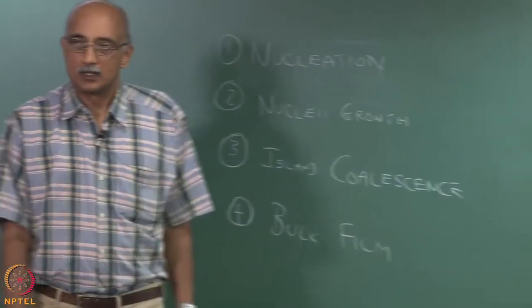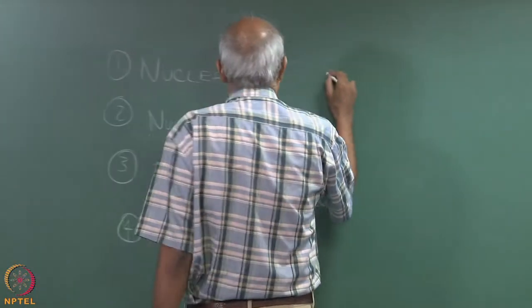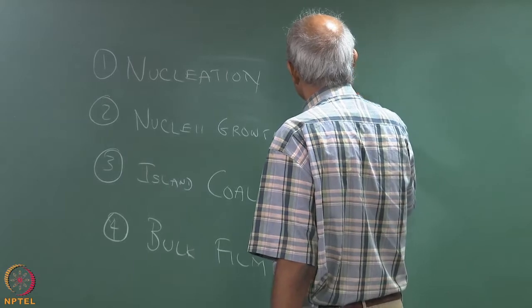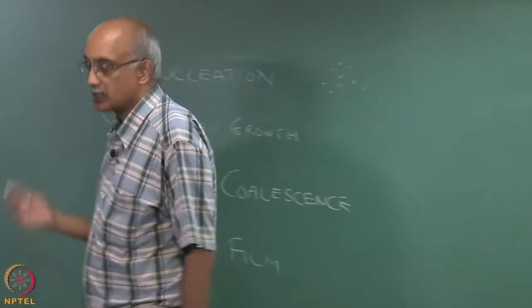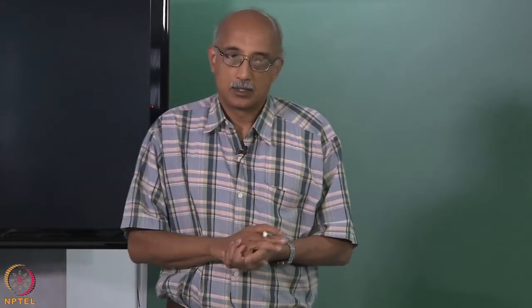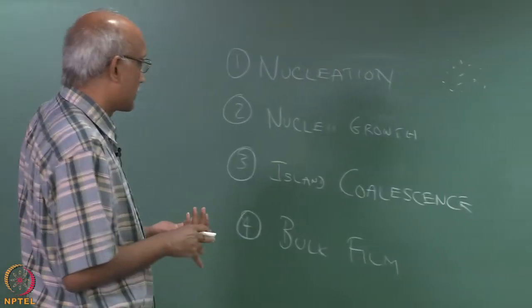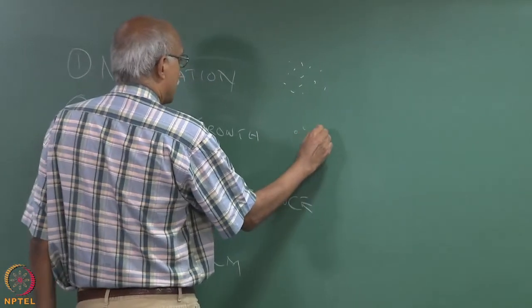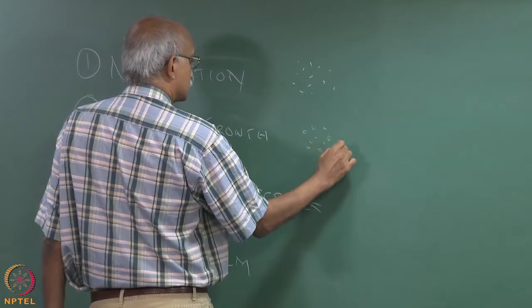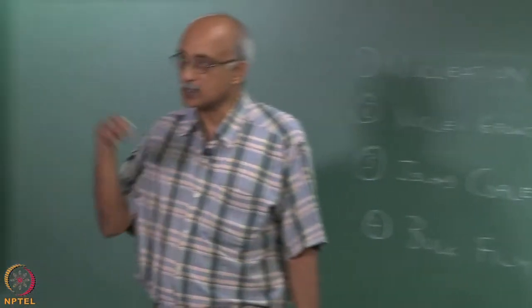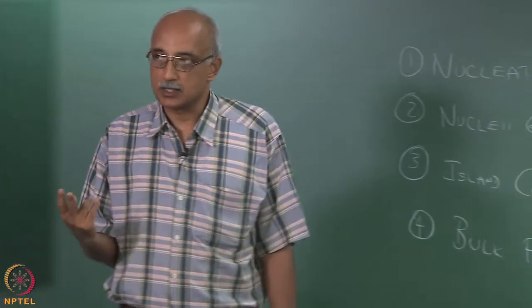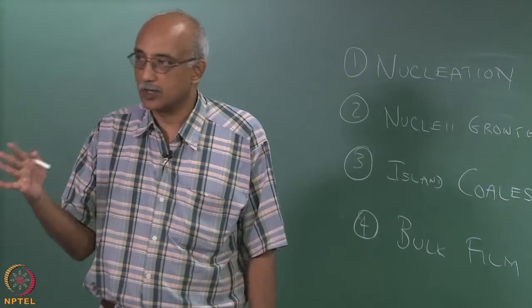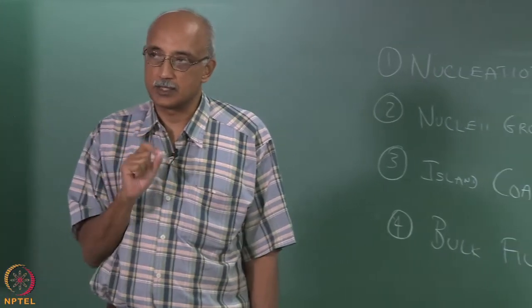As the name suggests, initially what you form are these isolated nuclei on the substrate, which happens essentially because of heterogeneous nucleation as the vapor phase comes in contact with the energized solid substrate. These nuclei are likely to be of the order of a few angstroms or tens of angstroms. As more deposition happens, eventually these nuclei start to become larger as they adsorb more vapors that are depositing onto the surface. So that's the second stage. It's a transition stage where you still haven't really formed a film. These are still isolated locations where the condensate exists.